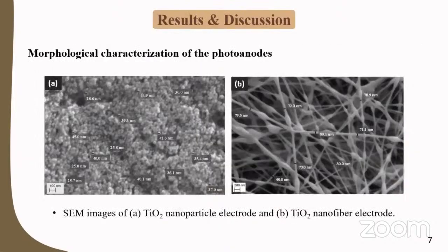Results and discussion. These scanning electron microscopy images show the top view of the TiO2 nanoparticle layer in figure A and the top view of the nanofiber layer in figure B, and the average diameter of the nanofibers appears to be between 30 to 80 nanometers according to figure B. This nanostructured layer enhances the light absorption of the photoanode by multiple light scattering.